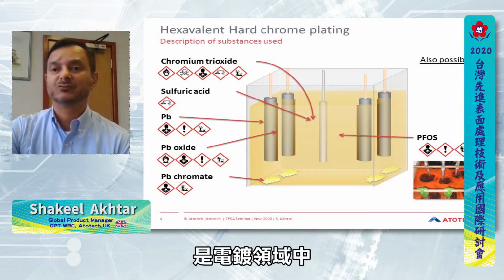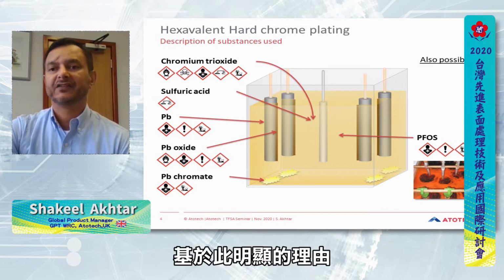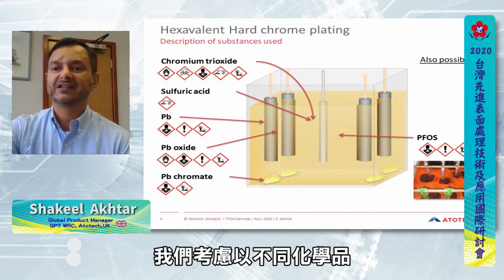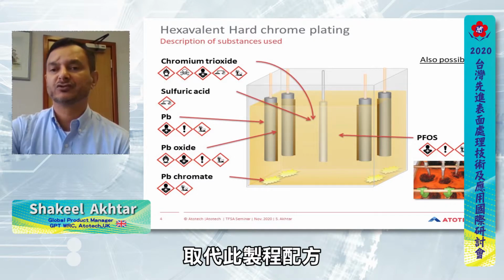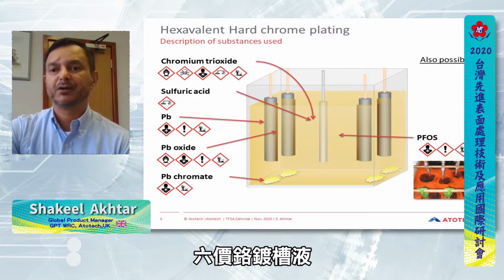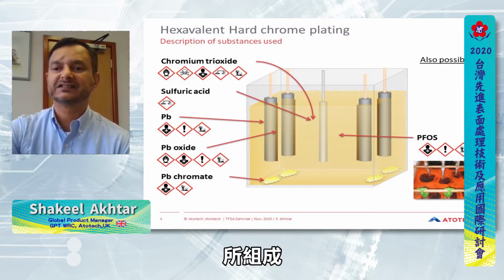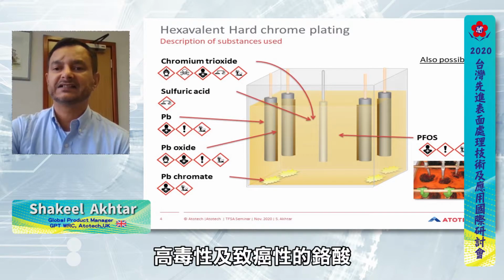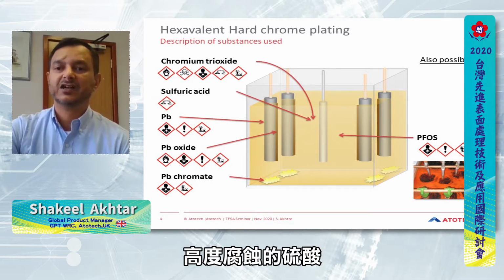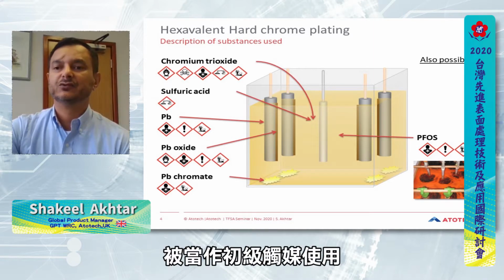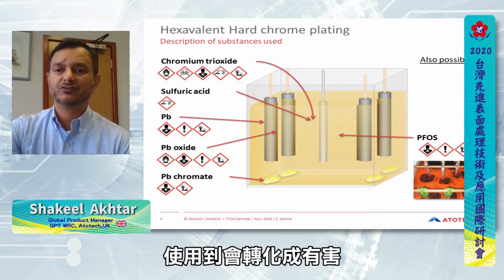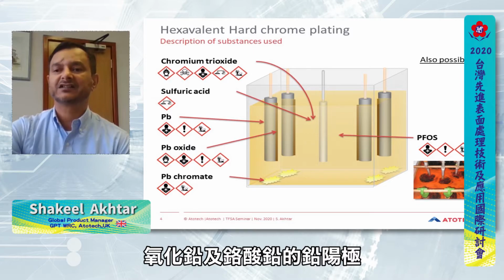Hexavalent chrome plating is one of the most hazardous and dangerous processes in the field of electroplating. The reason for this is clear when we consider the different chemicals that constitute the process formulation. The bath is composed of some very hazardous substances such as chromic acid, which is considered a very toxic and carcinogenic chemical amongst other hazards. Sulfuric acid, a highly corrosive chemical, is used as a catalyst in the bath formulation. The process also uses lead anodes, which are converted to lead oxide and lead chromate during the plating process.